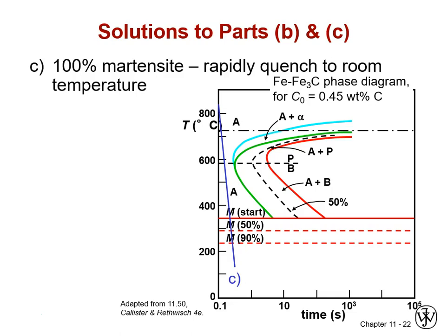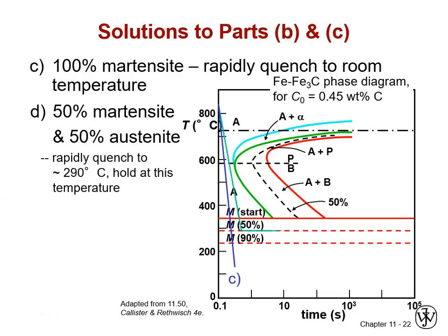So it's always better to be able to form what we want with slower cooling. Besides the fact that in a thick part, it just may not even be possible to cool the center that quickly. So shifting the onset rate of those decomposition phase transformations over to the right is called increasing a steel's hardenability. And that just means it's easier to form 100% martensite.